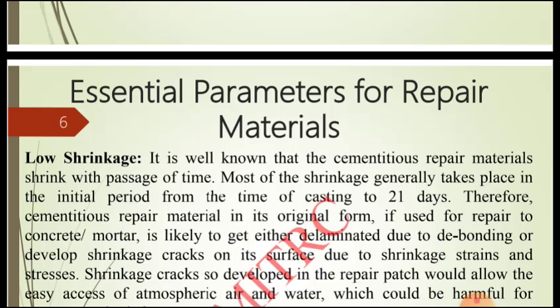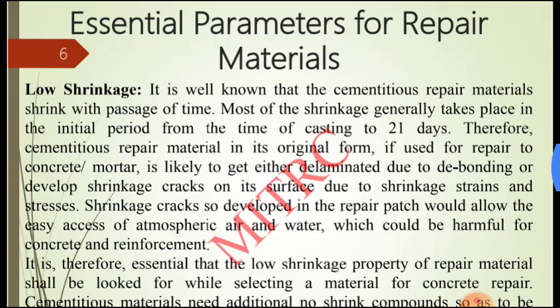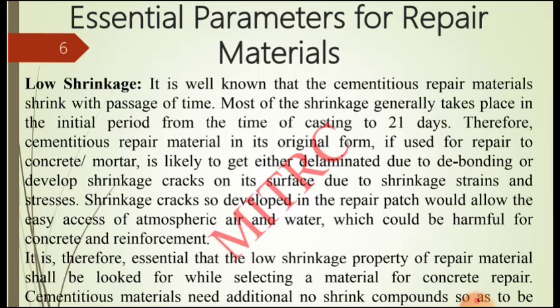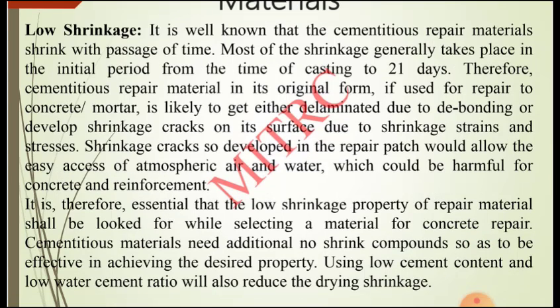Shrinkage cracks developing in the repair patch would allow easy access to atmospheric air and water, which could be harmful for concrete and reinforcement. It is therefore essential that the low shrinkage property of repair material shall be looked for while selecting a material for concrete repair. Cementitious material needs additional no-shrink compounds so as to be effective in achieving the desired property. Using low cement content and low water cement ratio will also reduce the drying shrinkage.